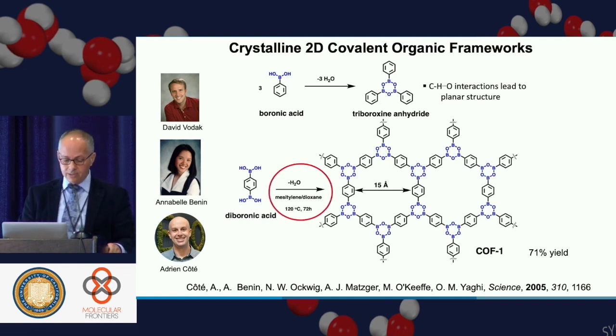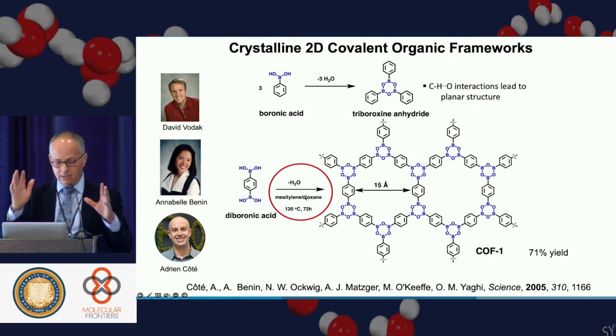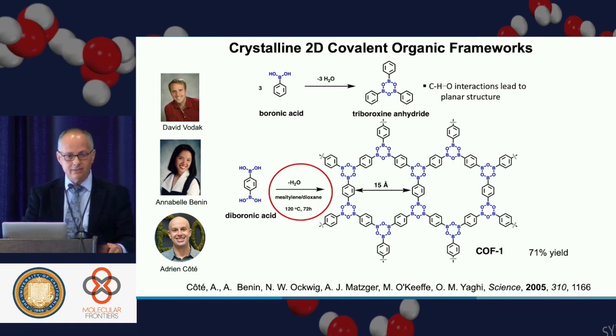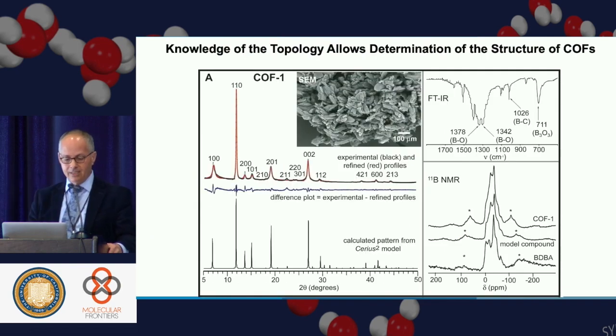So these are the conditions under which she found that they work, because we realized that water is a byproduct, and these were done in sealed tubes. And so if you control the pressure of water in the sealed tube, you control also the reversibility of the reaction and the microscopic reversibility of the reaction. That was the key to making these in crystalline form. So it turns out this is the kind of recipe that people use now to make many, many COFs, not just from this linkage, but many other linkages. So that hump you see here turned into this sharp X-ray powder diffraction, which matches what we anticipated.